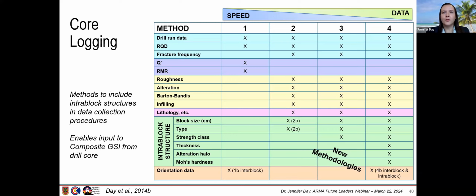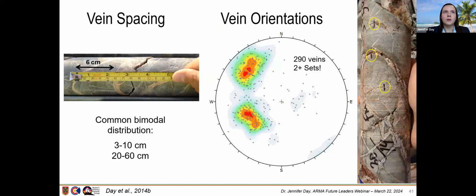And then in methods 3 and 4 of the core logging, really method 4, I looked at adding more information about the thickness of the veins, alteration, hardness, and then orientation as well for oriented core. And so from the most rigorous type, method 4B, where you've got orientation data and spacing data from the drill core, you can start to get that information, which would enable you to use that as input for discrete fracture networks or other discrete modeling of vein elements.